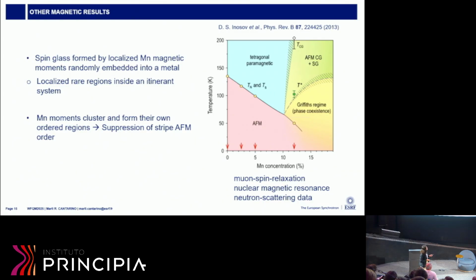Neutron scattering data probes the magnetism of this doping phase diagram. What they see is a spin glass, cluster glass, and supposedly a Griffiths regime close to the quantum critical point. This spin glass is formed by localized magnetic moments randomly embedded into a metal, forming their own order without interfering much with the iron order. This also aligns with the fact that there is no direct doping of the iron bands, and it explains the suppression of the antiferromagnetic transition temperature.